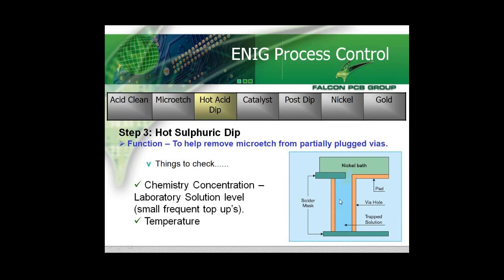Basically, what happens, we tend to find, is that the actual nickel starts to deposit at a much thinner rate than what we have in a normal pad. And it's not unusual to see nickel thicknesses on microsection analysis on skip plating of roughly between 1 and 3 microns. Again, at that level, it's porous and copper migrates through.